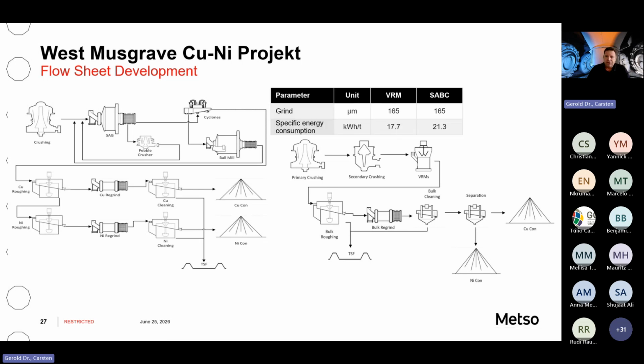And taking a look at the grinding advantage, in this case we had only a 20% reduction. But considering that this mill is so far off anything, the cost saving for providing the energy is massive. It was one of the first hybrid projects. The target was to go with solar power, wind power, and accumulators to basically run the complete project. And this is also one of the reasons to decide for the VRM, because to utilize renewable energies, you need a flexible grinding system. That is very difficult to achieve with a wet tumbling mill. But the vertical roller mill, as all the main process parameters are online controllable, can be easily adjusted to the conditions that you have.